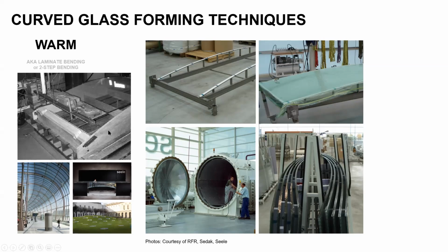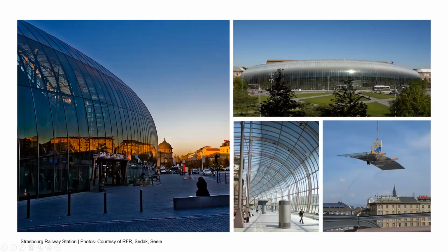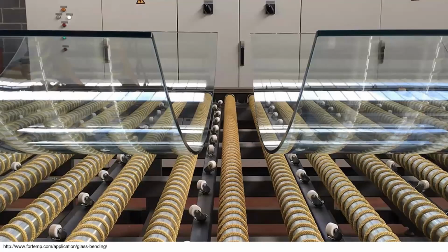And so the long-term behavior, I guess, of the performance of the interlayer at the interface is critical with that technology. That has been used for the Strasbourg rail station in France. These are the panels right after fabrication, and these are the panels during installation. This is a system that has internal spring back forces, and so you want to be able to capture them and also understand how long the interlayer is going to be maintaining these components in shape. And I did some research about it. I'll describe it down the line. Looks like I'm still in the general presentation and not yet in the weeds quite there.